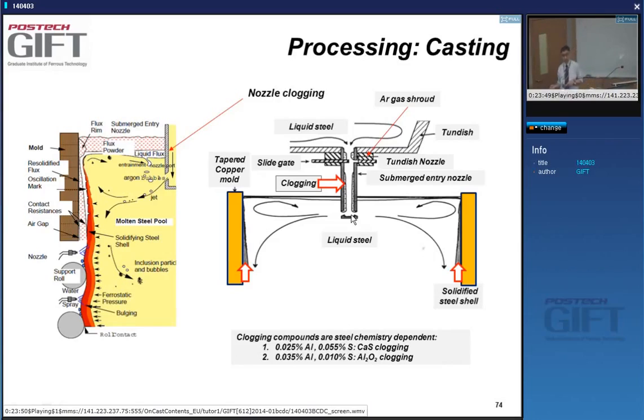If you've added too much calcium, yes, you can have problems with calcium sulfide. That can also give you clogging or abrasion, and the abrasion is again in this tube. When the liquid moves out, it goes with high velocity sideways, like shown here.